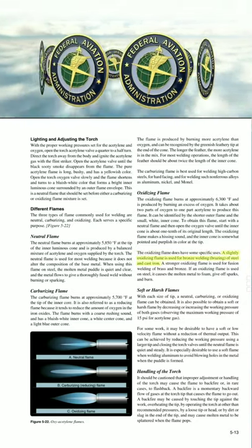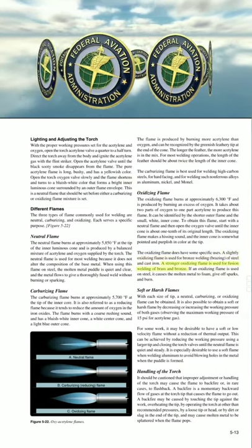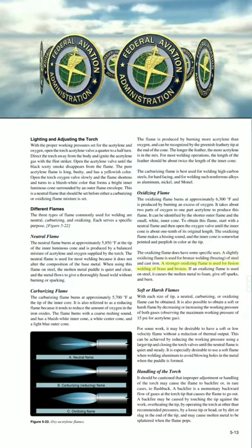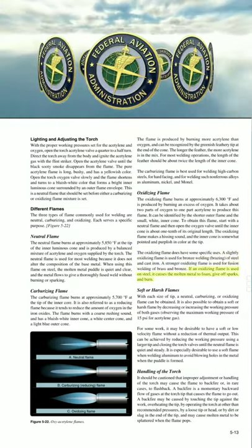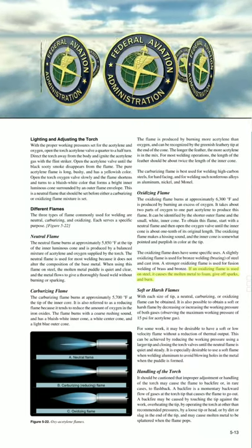A slightly oxidizing flame is used for bronze welding, brazing, of steel and cast iron. A stronger oxidizing flame is used for fusion welding of brass and bronze. If an oxidizing flame is used on steel, it causes the molten metal to foam, give off sparks, and burn.